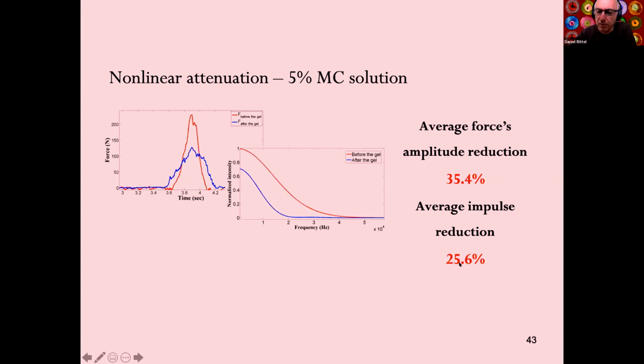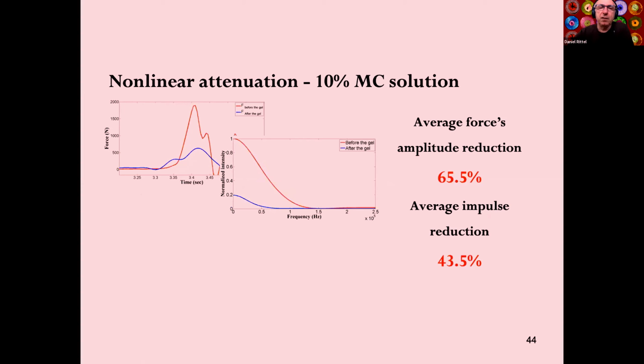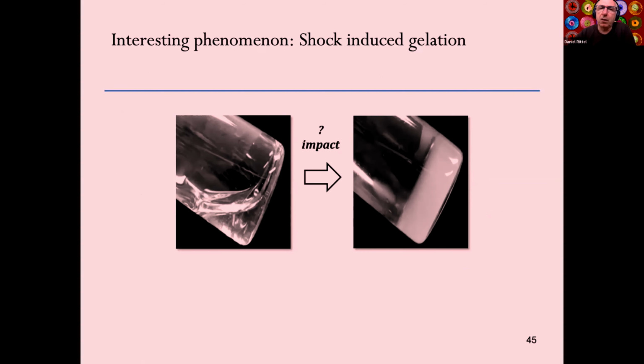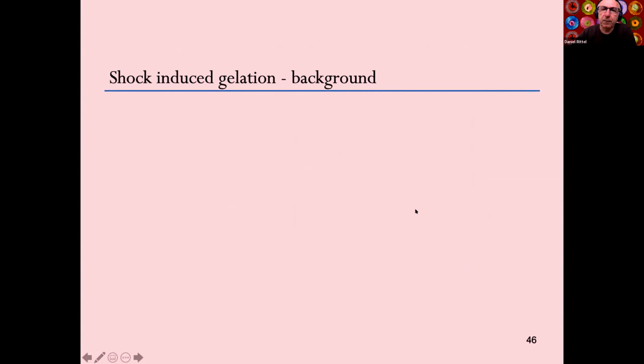Of course, those numbers have been refined and we're still working on generating much better statistics than those results. If we increase the solution to 10%, then we reach a very strong attenuation of the force and the impulse. So this material, which is basically water with a little bit of powder, has a very strong shock attenuation power. How does that come? Where does it come from? That's the liquid, that's the solid. So what do we do?